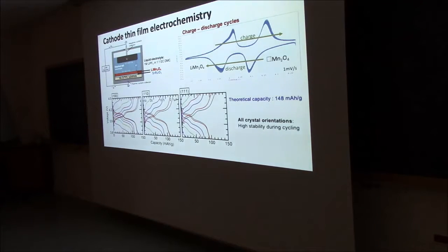So this is what we're optimizing now, so that we can do these measurements while cycling. But it's fully delithiated in this state, and there it goes to one and the other. And the values that we're getting is what you would normally expect as well, how much capacity you get out. But that doesn't have an effect on the stability of the structure at some point, like if you deplete after too many cycles? This crystal structure is not layered, so without lithium it's still a stable structure. In a bunch of these materials where you do this intercalation, you can do this over and over; it's stable as long as there are no other reactions taking place. And what we'll show you in a minute is that you can cycle it very often, and it's still very stable.